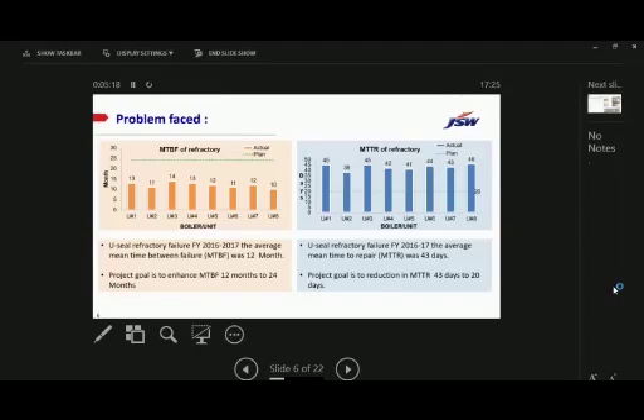In the year 2016-17, the refractory failure was so high that the mean time between failure was just 12 months. As well, due to the high volume of repairs and maintenance, the MTTR was also quite high, at 40 to 45 days. It has been targeted to 24-month MTBF and 20 days MTTR by the change of maintenance practices.